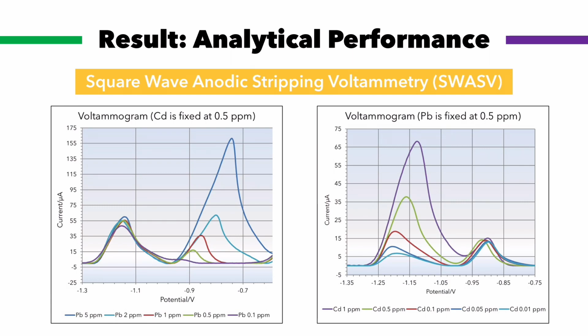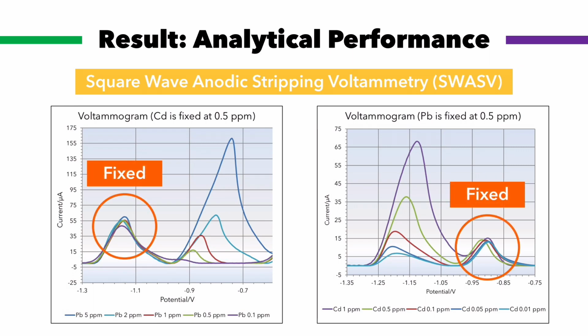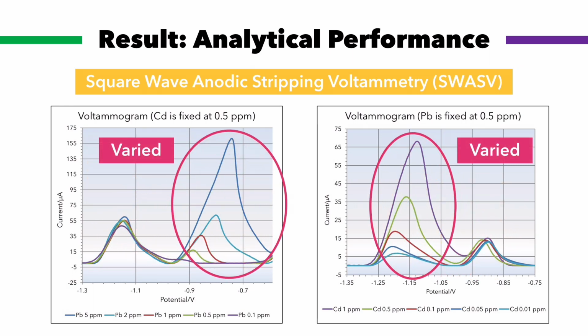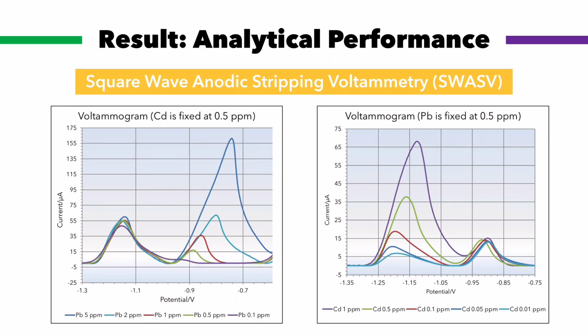The concentration of one was fixed and another was varied. Since the current of cadmium is always significantly higher than the current of lead, to be sure that peaks can be observed properly with no overlapping, the following conditions were chosen. Fix cadmium at 0.5 ppm, then vary lead. On the other hand, fix lead at 0.5 ppm, then vary cadmium.